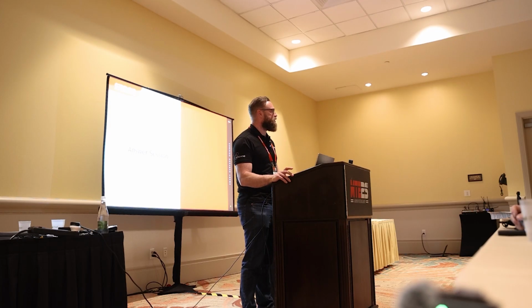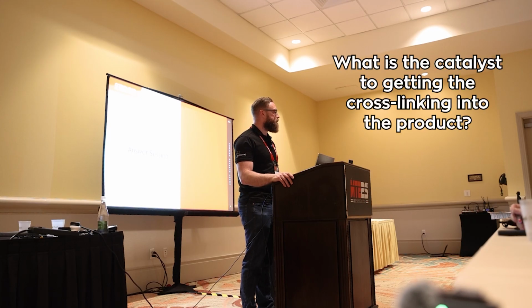And sorry, there's a second part to your question, wasn't there? What is the catalyst to get the cross-linking in the product? The catalyst is moisture in the air. We use a moisture curing catalyst. That is why it's in a solvent, and the solvent is water-free. There's no actual additional catalyst required. They're so reactive by themselves that when they get exposed to air, they'll just start cross-linking and reacting.